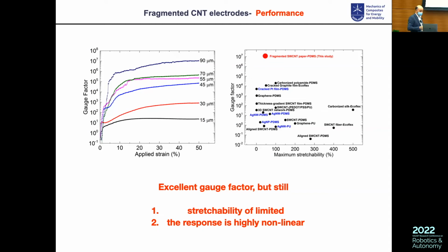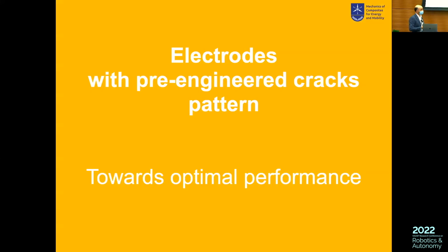So how can we restore the stretchability and everything? You can do this now by engineering your cracks. That means in this first part of the presentation, the cracks are what you call quasi-random cracks. That means you leave it to the micromechanics of cracking of your film. But now you can design your cracks. You can decide where you are going to put your cracks. So this is in two slides what I want to show in the second part.